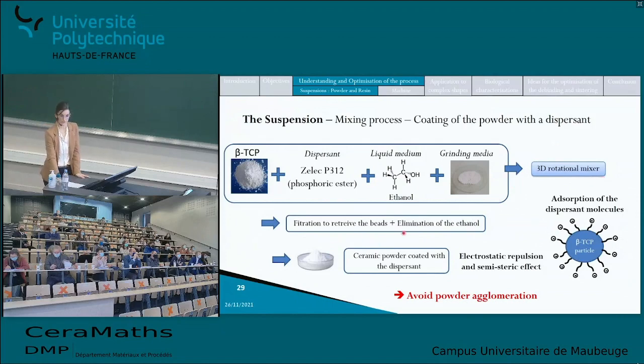Well, the dispersant adsorbs around the β-TCP particles, providing charge on its surfaces and providing electrostatic repulsion. Also, this dispersant can provide a semi-steric effect, but not a complete steric effect, because the molecules of this dispersant are very short. So all of that was made in order to avoid powder agglomeration.